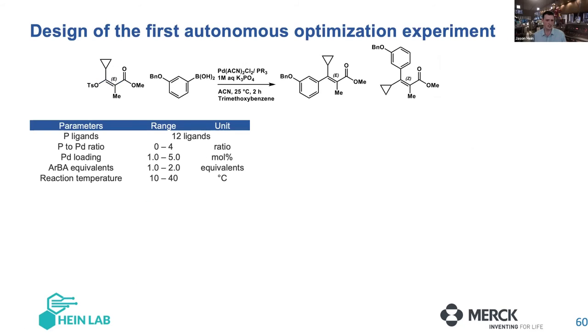To scope this out, we said, look, the knobs we're going to change: we're going to have these 12 ligands, a palladium to phosphorus ratio, a palladium loading, we're going to change the aryl-boronic acid equivalents, and we're going to manipulate reaction temperature. So we have a series of continuous variables, things that have numerical coefficients. But we also have categorical variables, like the ligand, which does not have a numerical value directly associated with it, and we wanted the ML algorithm to be able to treat that space too.